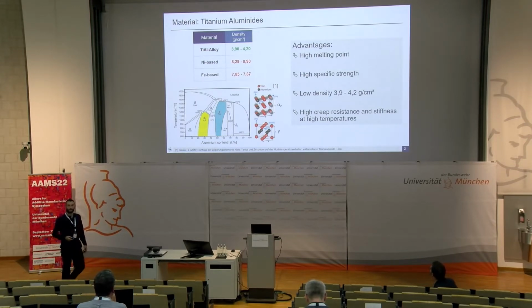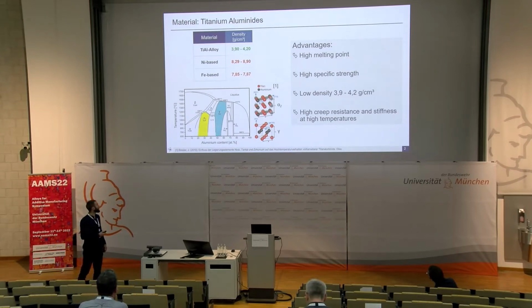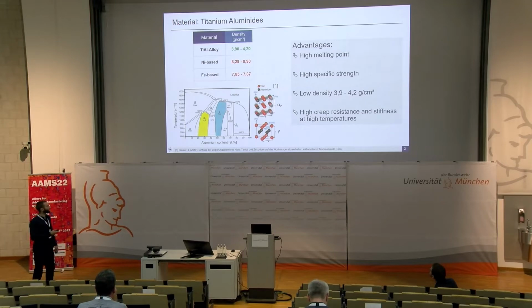We are using these materials in low pressure turbine blades, and here we have the density. I already mentioned we have a really low density in these materials compared to maybe nickel-based or iron-based materials, which are also used in low-pressure turbine blades. There are more advantages of this material. It has a high melting point, a high specific strength, and also high creep resistance and stiffness at really high temperatures. On the left side, we see the phase diagram, and we see the 2 main phases, the alpha 2 and the gamma phases. And we are working with a material with a phase composition at around 48% aluminium content.